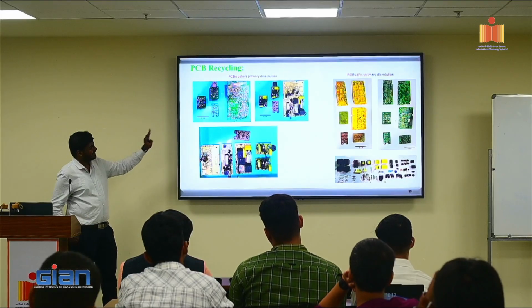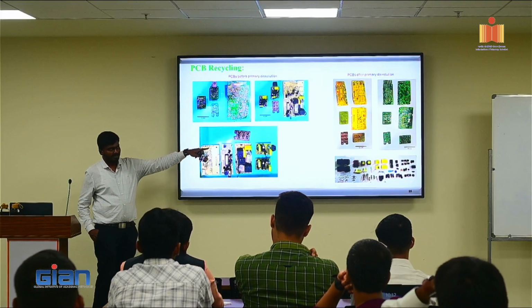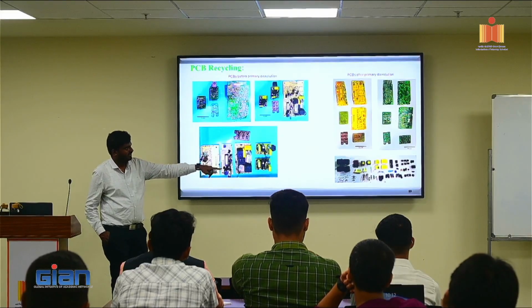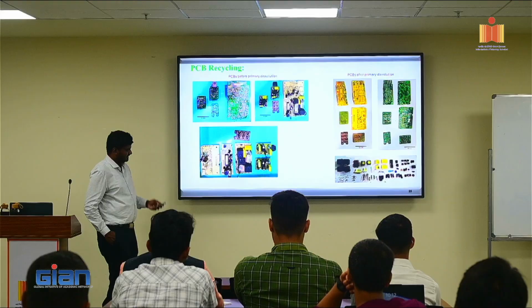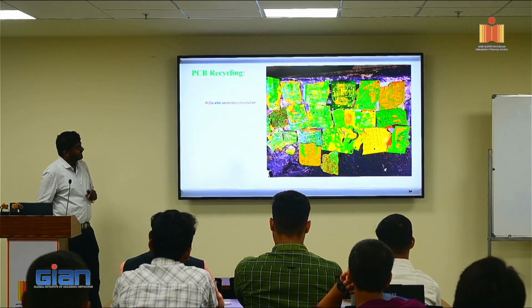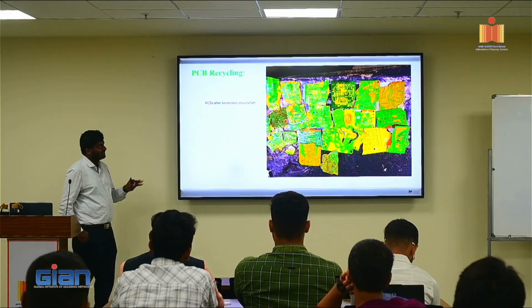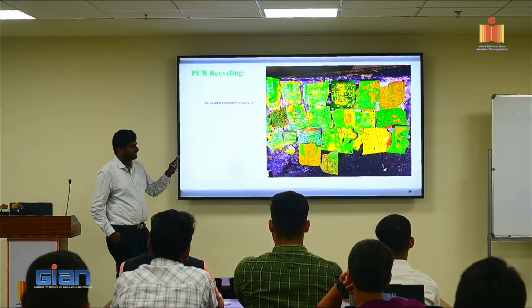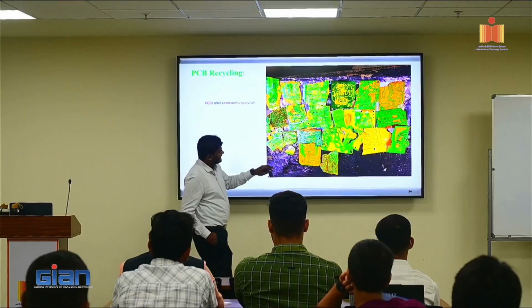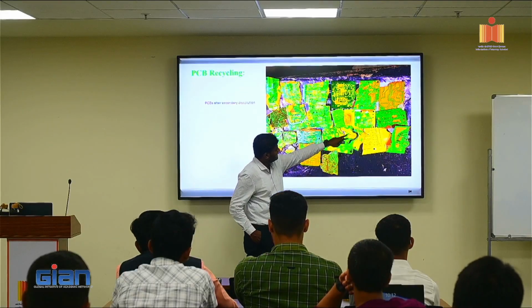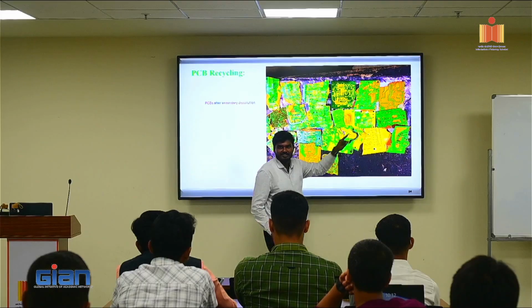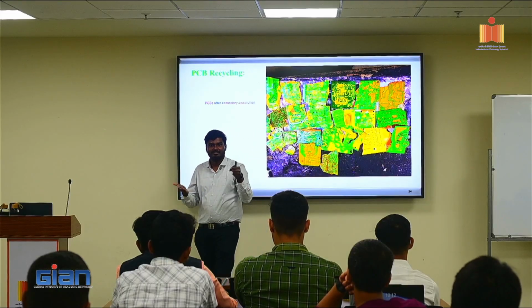So these were the PCB boards that I have taken. After primary dissolution, you can see that all the electronic components were separated and we have this resin. Similarly, you can see this is for different kinds of PCB boards. This is the final unreacted resin that we got. You can also see that there are layers of this epoxy which are peeled off. So here it clearly shows it's not reacting with acid, it's just getting peeled off from the board.